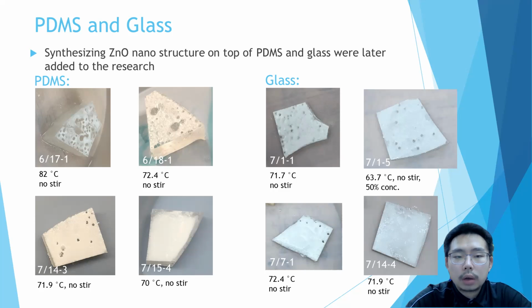So far, we found that using ultrasonic baths to clean it first and then treat it with oxygen plasma gun could greatly reduce the air bubbles. However, the distribution of the zinc oxide was still not very even.